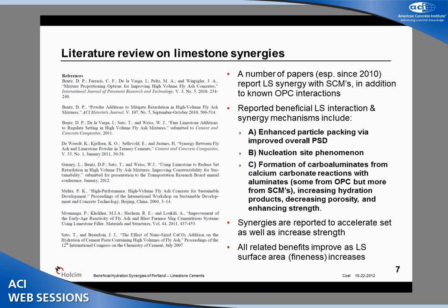When you start doing literature review on such synergies, there are quite a number of papers that have been published by authors all around the world on the subjects. Many of them have investigated primarily the setting time influences. It's been found that limestone in the system can be a very useful tool in mitigating the otherwise retardation issues that might be associated with, for example, high volume fly ash mixtures.